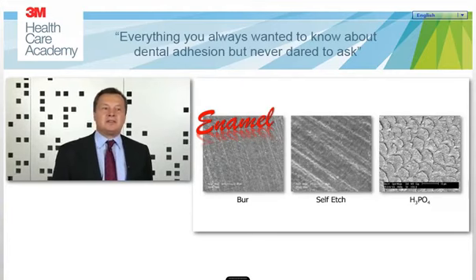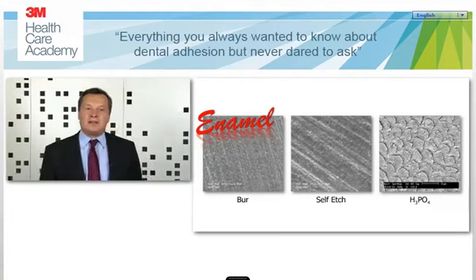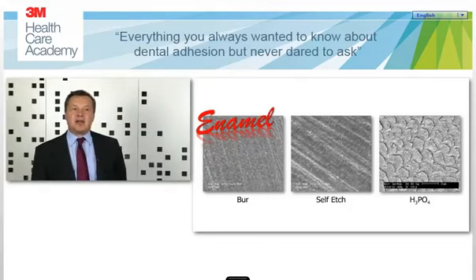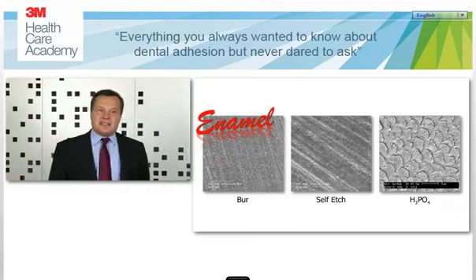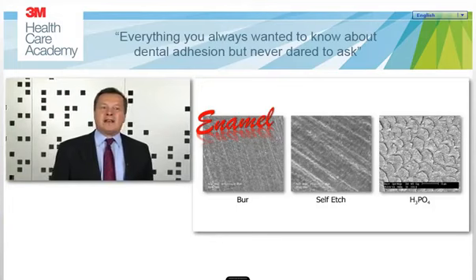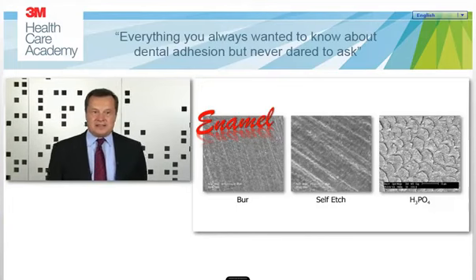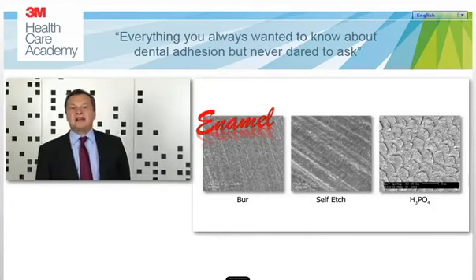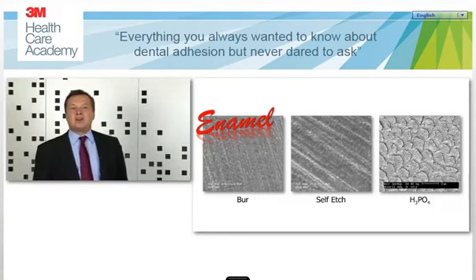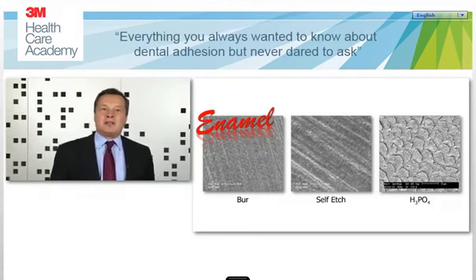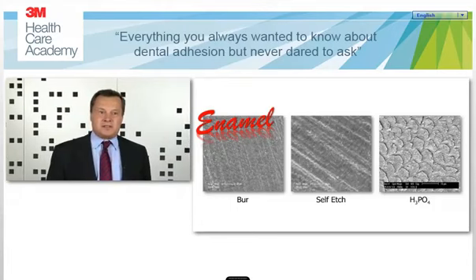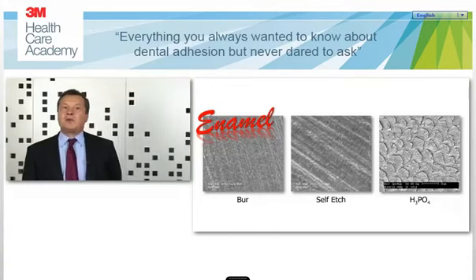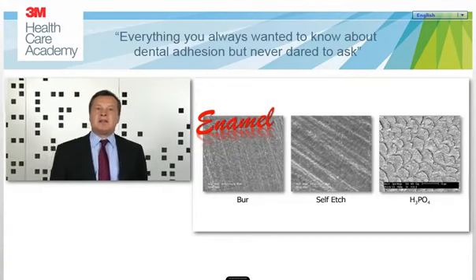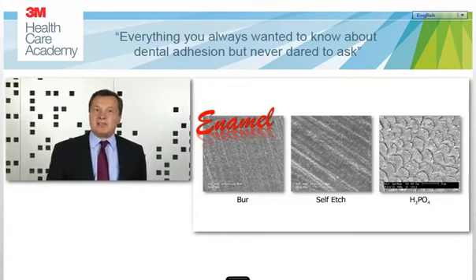You can see that due to the quite low aggressivity of this self-etching primer, the surface is cleaned, but it is not aggressively attacked by this acid. And on the right-hand side, you can see the action of a very aggressive phosphoric acid on enamel. This phosphoric acid not just removes the superficial contamination of the surface, but it also attacks the substrate, which is enamel, and it exposes enamel prisms.